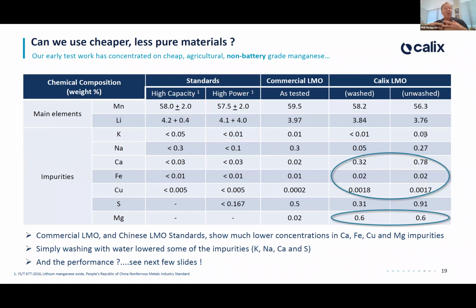We're not starting with high purity materials. And this table here, I know it's a little complex, but I'm trying to describe the different impurities in materials. In these two columns, you can see the standards, these are Chinese standards actually, in place now for lithium manganese oxide materials. These impurities are just elements like potassium and sodium and calcium and iron, and they've got to be very low. So in typical battery material processes, you've got to start with low impurities.